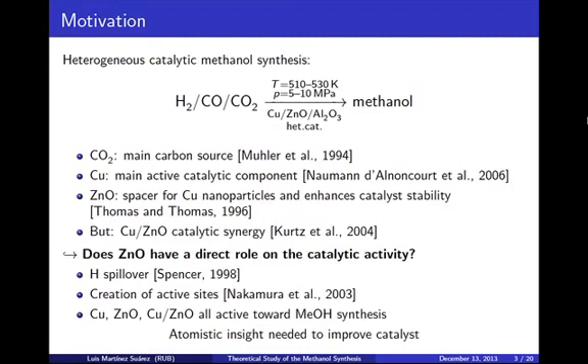In the process of the synthesis of methanol, a highly reactive mixture gas of hydrogen, CO, and CO₂ is circulated on the catalyst. Experimental evidence showed that CO₂ is the main carbon source for methanol. Copper nanoparticles are the main active component, and zinc oxide spaces the copper nanoparticles, enhancing catalytic stability. But also, zinc oxide shows catalytic synergy with copper, enhancing catalytic activity.